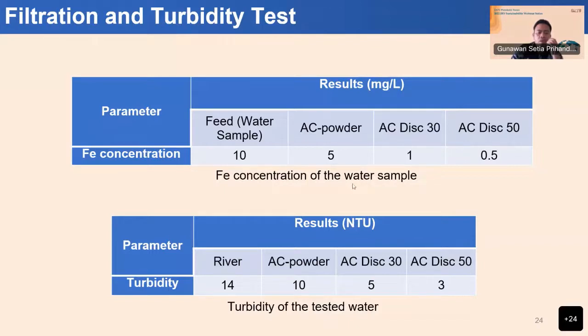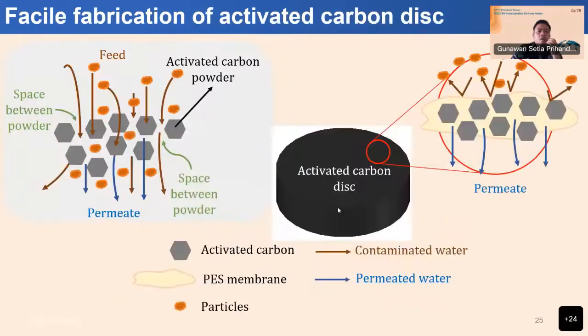So the same, good results come when we test the turbidity. On the river we have 14 NTU, and then once we have the activated carbon disc we have 3 NTU. So based on this we can say that the activated carbon disc is much better in filtration compared to the activated carbon powder.